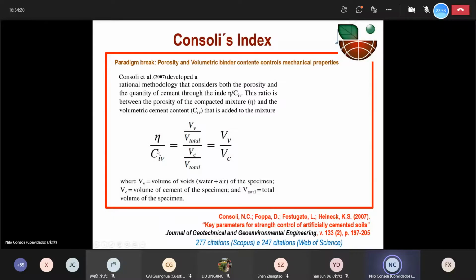And we have proved, in many years of research looking at it, that we could get an index here that is porosity divided by volumetric cement content that controls initially the strength of these mixes that we have with any kind of binder. But first of all, we use like Portland cement. This paper was published in 2007, and nowadays it has almost 300 citations at Scopus and 250 about that at Web of Science citation too.